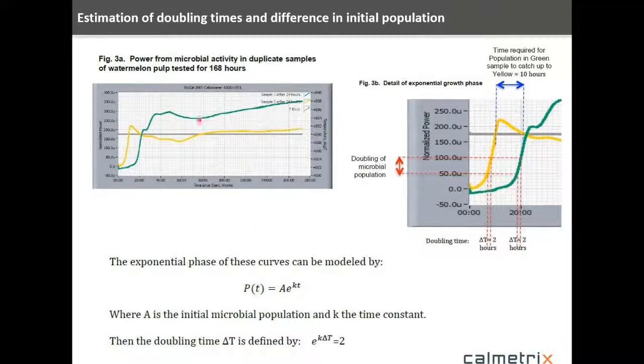And here's an example of that. This happens to be on watermelon pulp that we're working in concert with NC State on, and here two different samples. We're going to focus here on the initial part of the curve, and that's blown up over here. And so you can see here, if we look at the doubling of the population and we go to the curve and we extrapolate down, we can tell that in both cases, we had a doubling time of about 2 hours, but there was a lag between one sample and another of about 10 hours. So there was a different initial population. And how might we quantify that? Well, we can use the same equations that you're used to using. Here we're using a very simple equation.